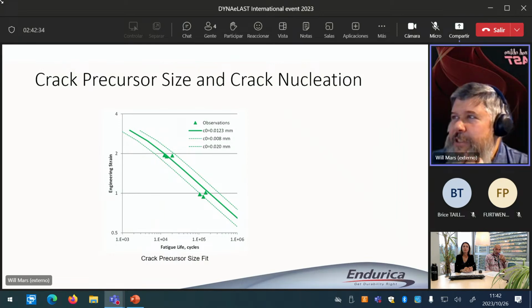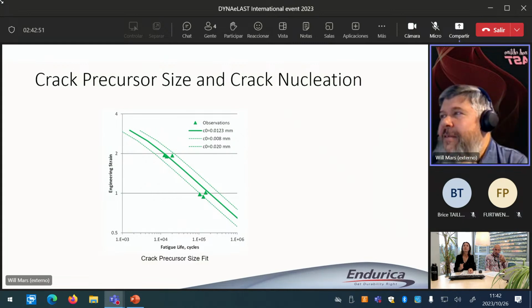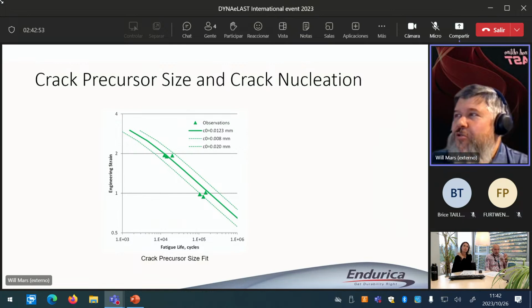This is a plot of the engineering strain versus fatigue life. These experiments were made on simple tension strips. The triangle data points are showing the actual experimental results. The theoretical line, the green lines that are drawn through the data, those are actually predictions of the fatigue model.